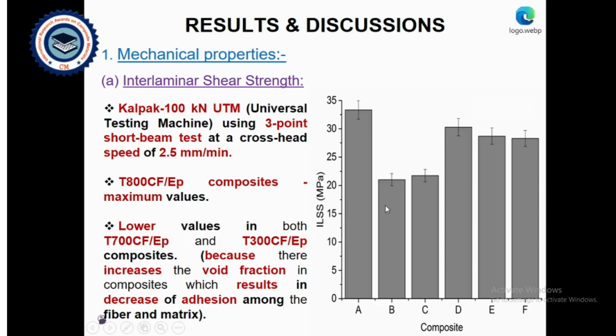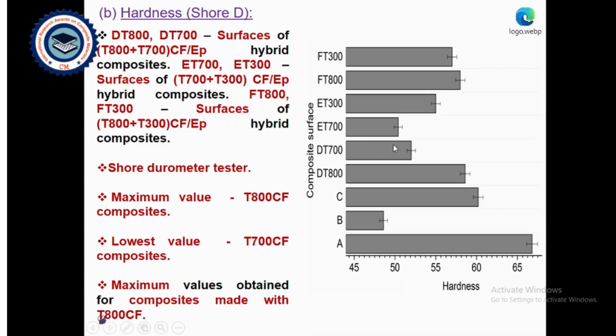If we observe the graph of composite combination versus the ILSS, that is the interlaminar shear strength, we can see that T800 composites provided maximum values. Low values were observed in T700 and T300 individual composites because there was an increment in void fraction in the composite, which results in a decrease of adhesion between the fiber and the matrix. Here we used a 3-point short beam bending test at a crosshead speed of 2.5 mm per minute. Next, the hardness.